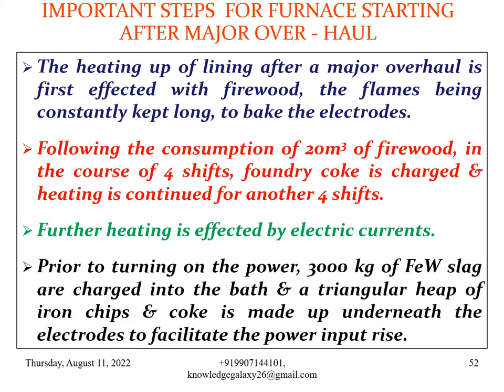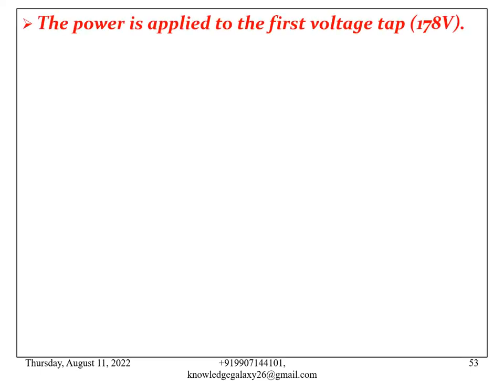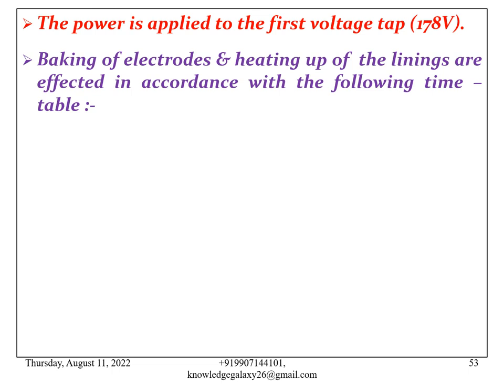Prior to turning on the power, 3000 kg of ferrotungsten slag are charged into the bath and a triangular heap of iron chips and coke is made up underneath the electrodes to facilitate the power input rise. The power is applied to the first voltage tab, that is 178 volt. Baking of electrodes and heating up of the linings are effected in accordance with the following timetable.